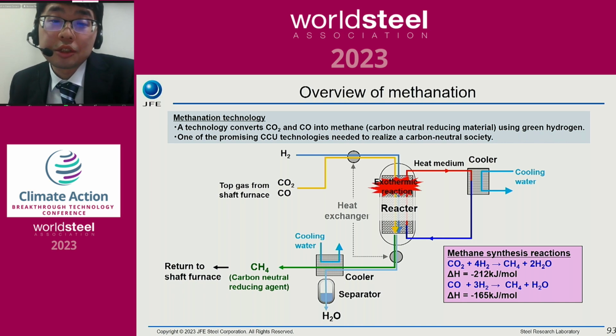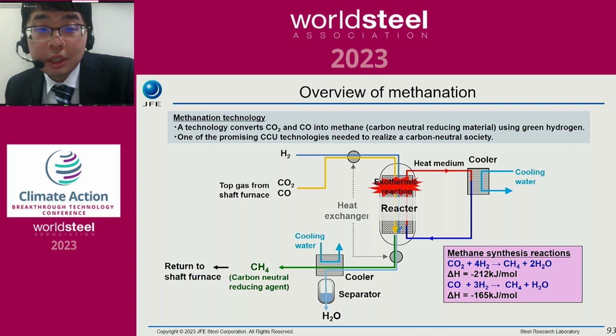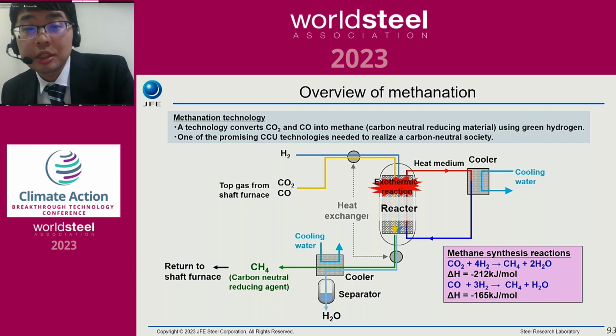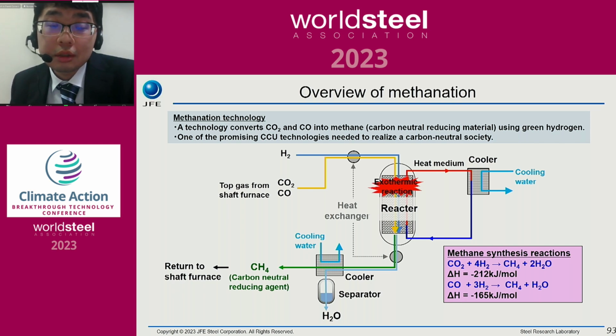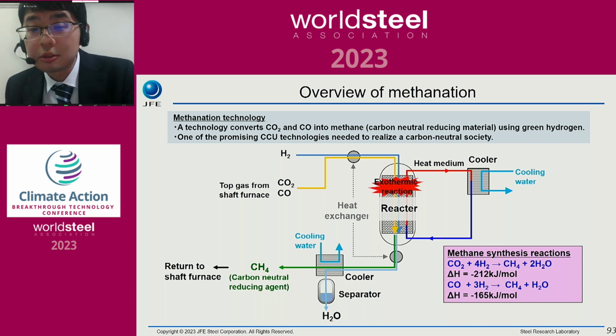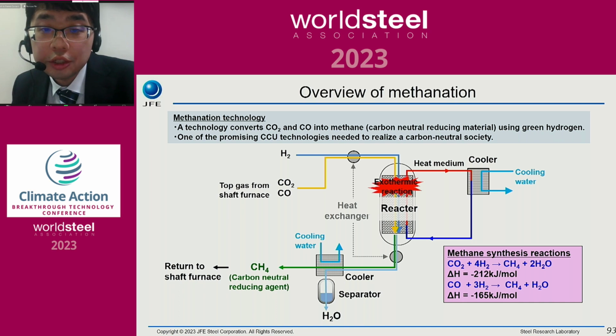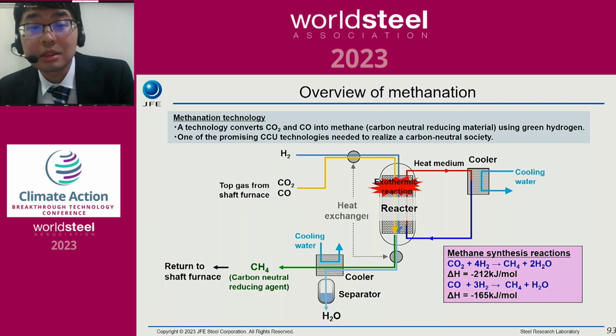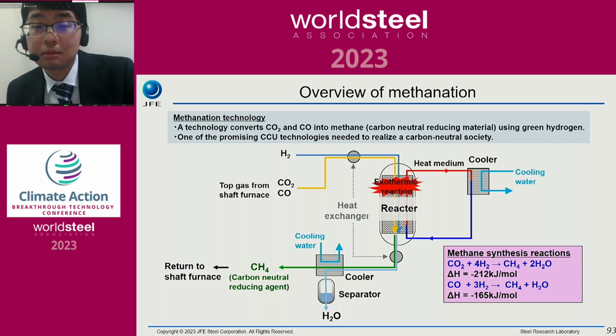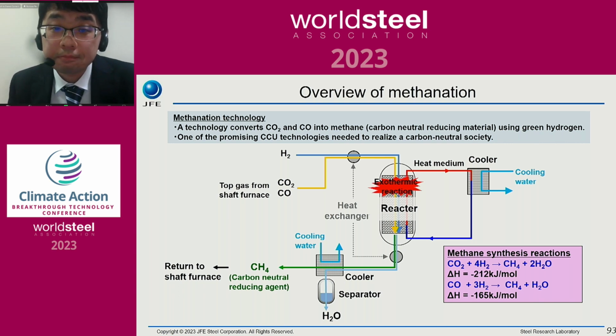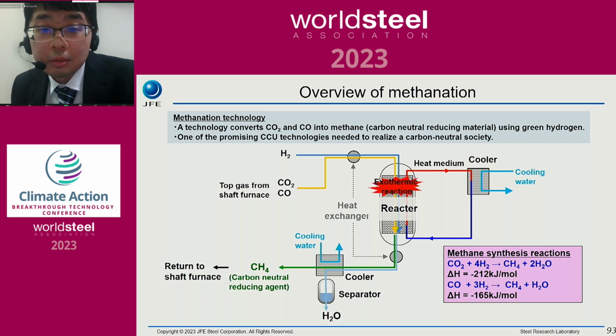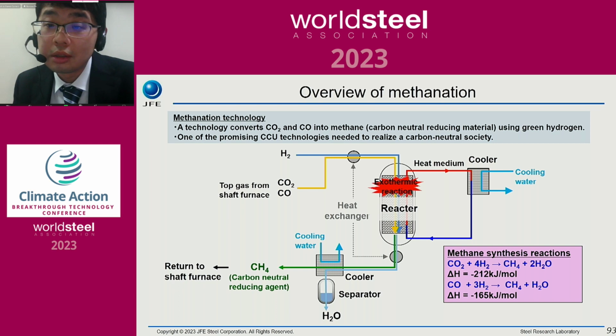Both are exothermic reactions, so gas cooling is required. And recovering of waste heat generated by the reaction is also important. After the production of the methane, the moisture in the gas is removed by cooling. We plan to investigate the reaction behavior of hydrogen in the catalyst bed using gas simulating the ratio of carbon monoxide and carbon dioxide in the top gas of a shaft furnace. And we are considering proposing appropriate reaction conditions and optimizing the configuration of the reactor as development elements.